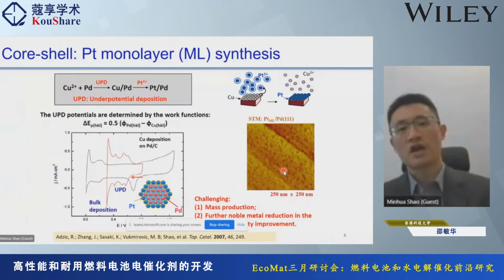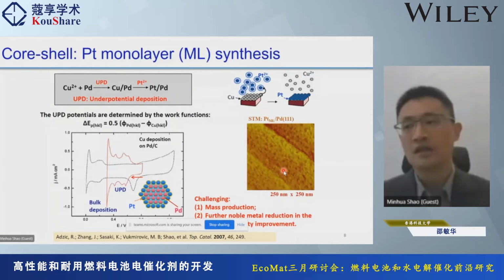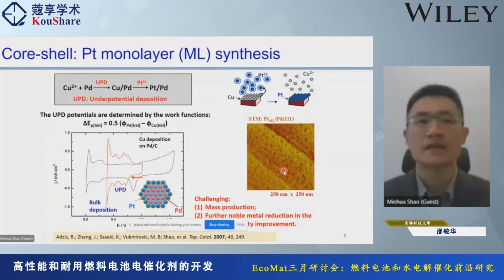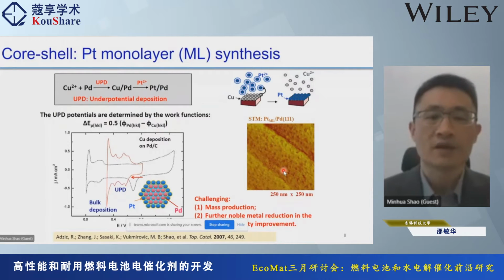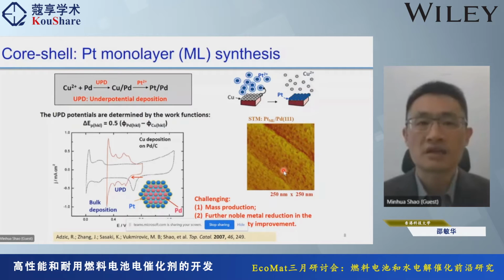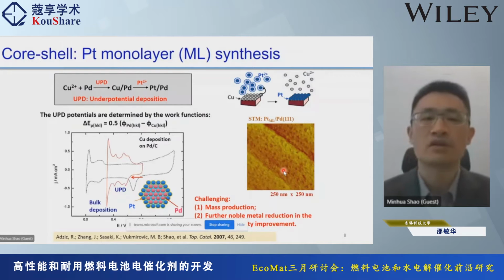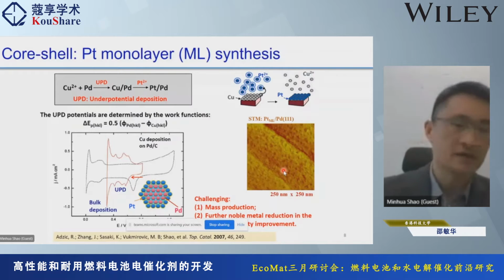So next, I'll talk about our approach. On the precious metal side, we started with a core-shell structure, because the fundamental rationale is that the reaction occurs on the surface. So if we can limit the platinum to the surface, and inside the nanoparticle use other metals, hopefully cheaper, then you have high utilization of platinum.